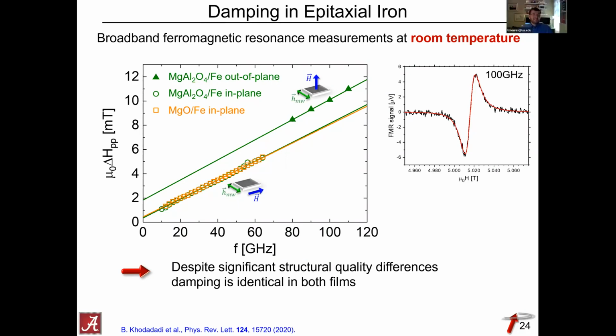Typically we see that in films that have perpendicular anisotropy. So there things can be different. For those films, if you have a system with a perpendicular anisotropy, you actually expect the inhomogeneous broadening to be larger in the out-of-plane configuration than in the in-plane. However, in this case, I'm actually not quite sure what's causing that. So we haven't looked into that in more detail, if that's your question.